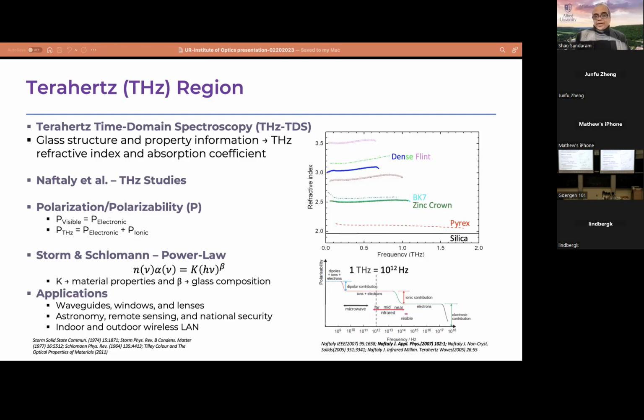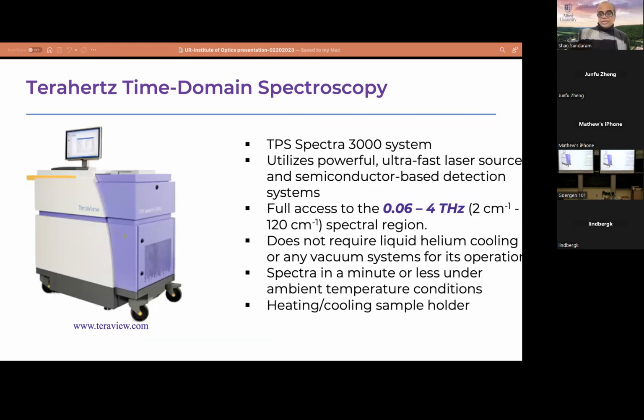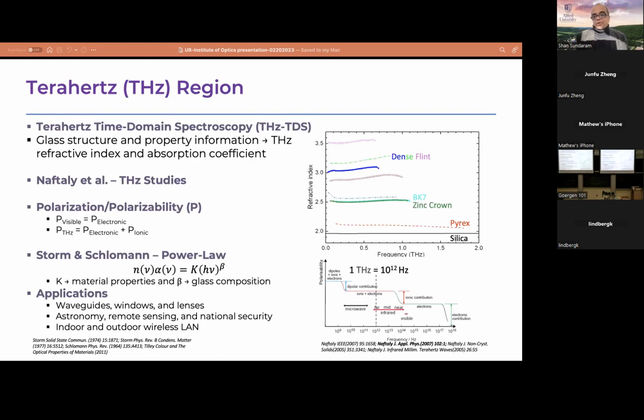And we also followed a major study by Naftali et al. This is a group at the National Physical Laboratory in the UK. They were the first ones to actually publish refractive index over a range of terahertz frequencies for selected glasses. So you would see some of the BK7, zinc crown, Pyrex, and silica, these glasses shown. You can see, the first thing that probably strikes you is where is the resonance? I don't see any resonance here because these are all disordered glass structures. But the good news is you can see there is a chemistry-dependent refractive index. You can see a whole range of refractive index for various glasses. So we may not be able to capture some specific resonance because those rotational symmetries are not happening in these materials. But we'll be able to measure the properties directly.